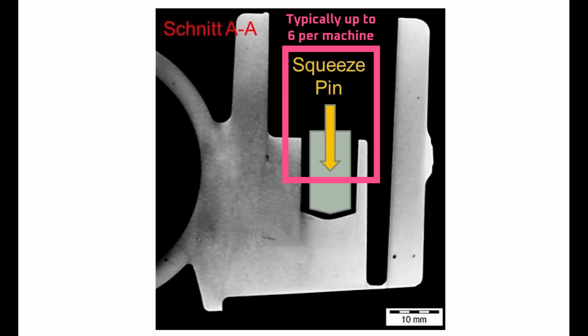Third, the lack of pressure means that typically, high-pressure die casting machines can only support up to 6 squeeze pins, but most use less, at around 2 to 4. Fourth, control of the pins is limited. That is, during the casting cycle, all of the pins squeeze at the same time. Lastly, beyond the pressure issues, conventional pressure pin systems generally have issues with the pins getting stuck due to corrosion.